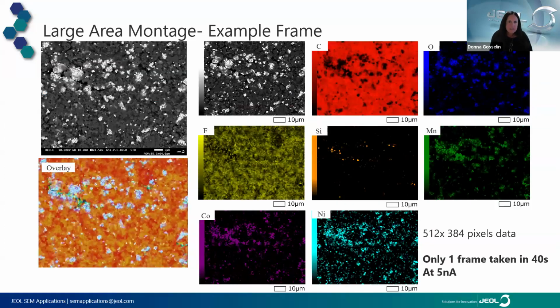And finally, here is an EDS map of one of those tiles, just to show an example. This was a medium pixel resolution image of 512 by 384 pixel data with one frame. It took about 40 seconds to collect at 5 nanoamps. So you can see we get quite a good resolution and good signal to noise. So we can collect this data in a fairly short time.